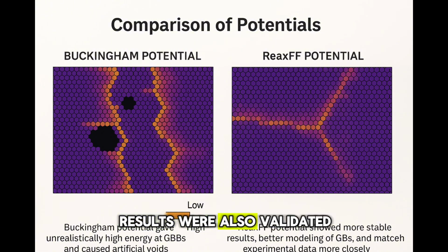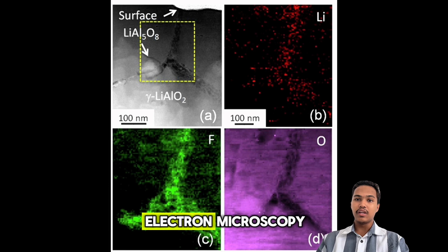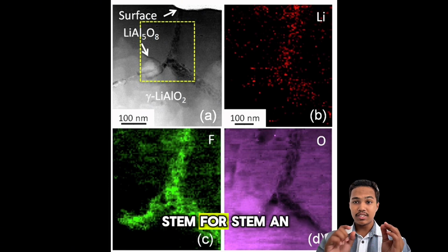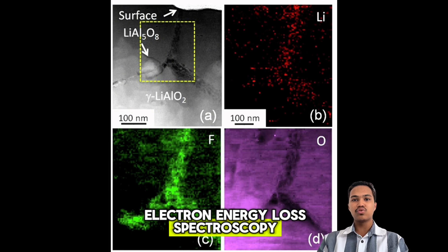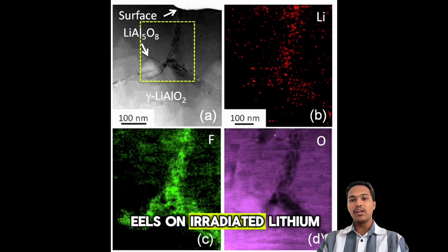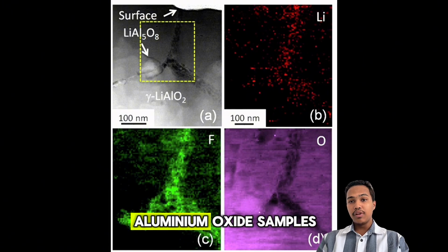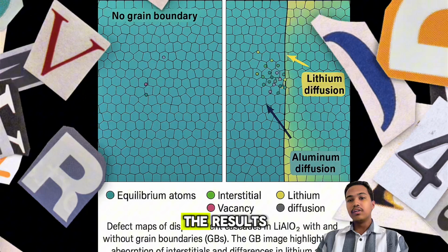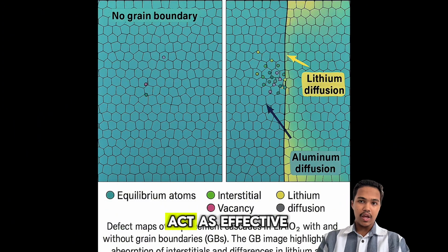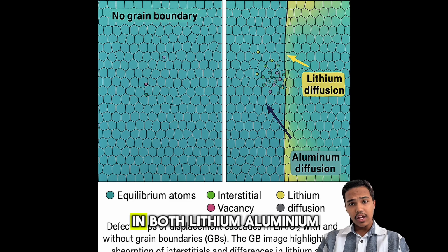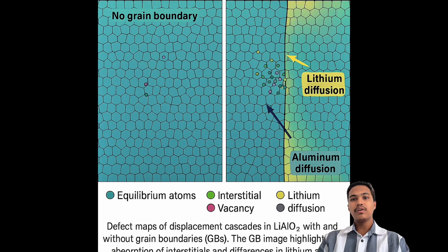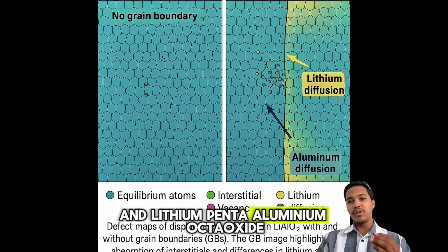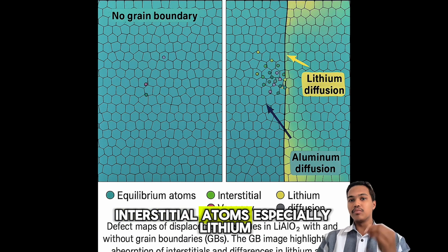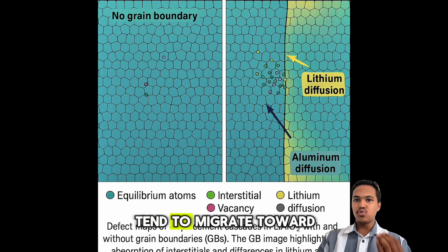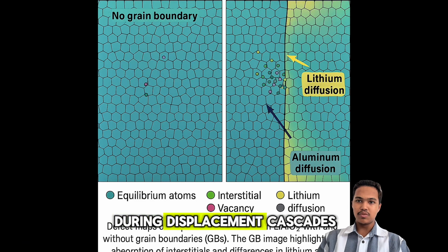The simulation results were also validated through a real-world experiment using scanning transmission electron microscopy, or STEM, and electron energy loss spectroscopy on irradiated lithium aluminum oxide samples. The results show that grain boundaries act as effective defect sinks in both lithium aluminum oxide and lithium pentaaluminum octaoxide. Interstitial atoms, especially lithium, tend to migrate toward the grain boundaries during displacement cascades.